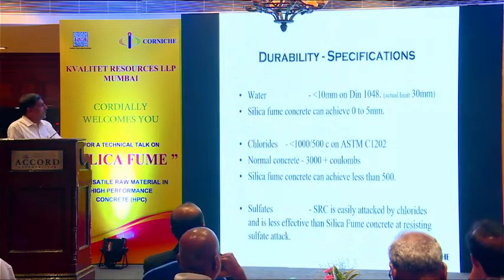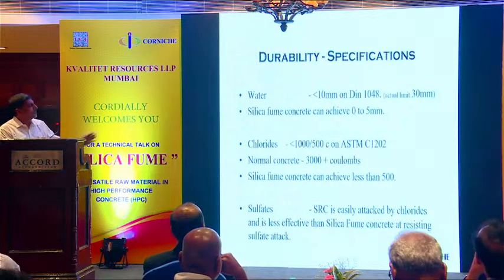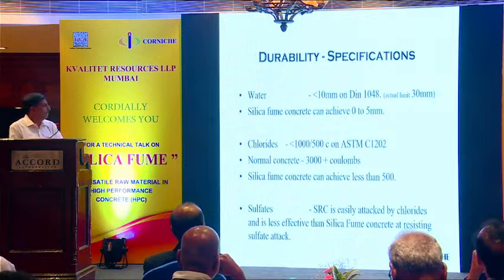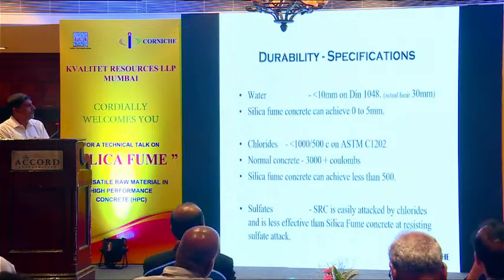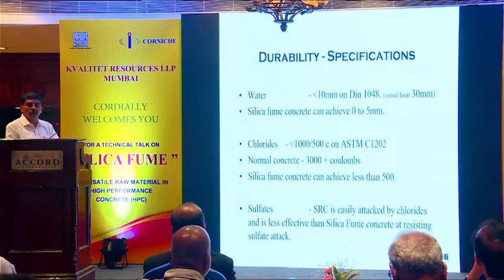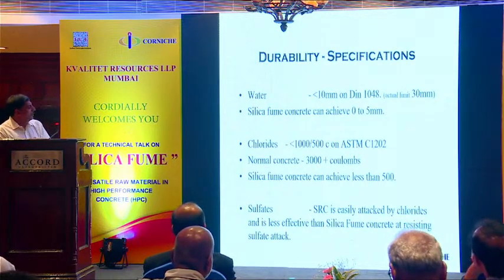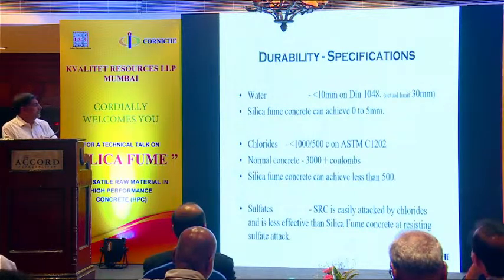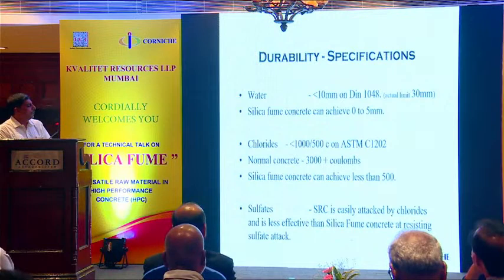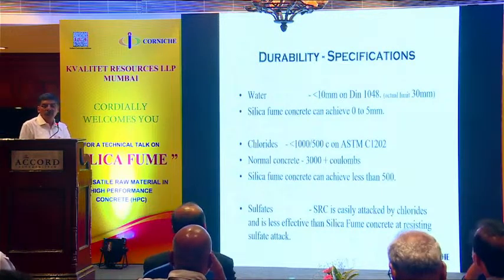So durability specifications, as per DIN, it asks for 30, but many designers are specifying less than 10 mm. Silica fume concrete can achieve less than 5 mm. In most of the cases, it is nil, less than 2 mm. Chlorides, they are specifying 1,000 coulombs in very aggressive environments. They are even specifying less than 750 coulombs.